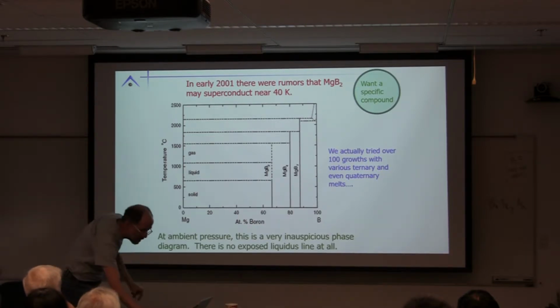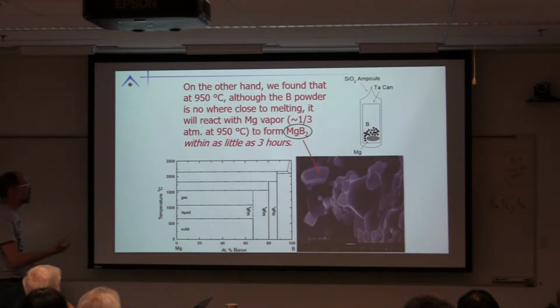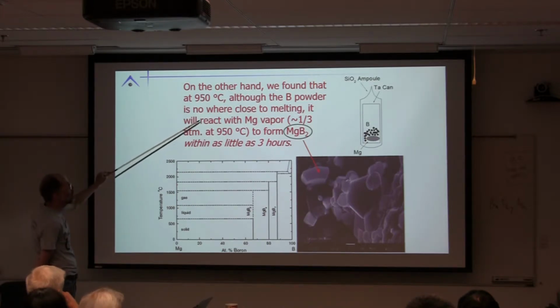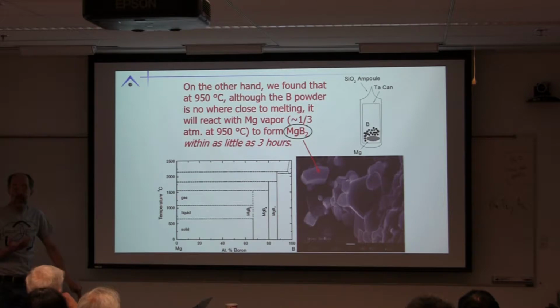On the other hand, with the tantalum tubes, with stuff that we had on hand, we rapidly realized that we could grow incredibly high purity MgB2 polycrystalline materials by just having high purity boron and high purity magnesium in a tantalum can, and at 950 you have a 1/3 atmosphere partial pressure of magnesium, and it sucks the magnesium out of the air. So you can get it by diffusion. Okay? And the key was having high purity boron. If you have low purity boron, then you have low purity MgB2 and you have sort of crap results.